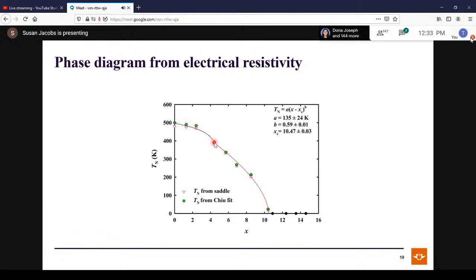Now over here, we see an inflection or a change in slope corresponding to close to 4 atomic percent vanadium. We speculated that this could be the transition from the commensurate spin density wave phase to the incommensurate spin density wave phase. It makes sense because over here you have no vanadium, and like I said earlier, vanadium is electron deficient. So as you add more vanadium, you're decreasing the size of the electron sheet even further, which means you're pushing the system towards incommensurability. So there's a good chance that this bend in the curve corresponds to a commensurate to incommensurate spin density wave transition.